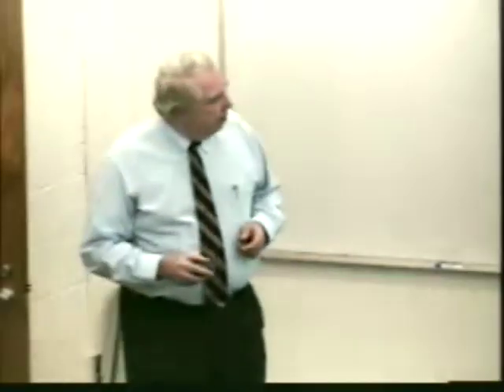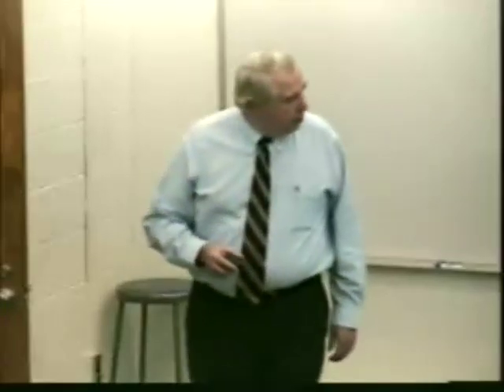There's one other interesting characteristic about this. General Electric has done a lot of design work on their liquid metal reactor. And in the case of their liquid metal reactor, where they have temperatures of 500 to 550 degrees Celsius, they have discovered, after lots of calculations and experiments, that the maximum size of their reactor can be about 1,000 megawatts electric. And the reason why is that as they go to higher power levels, there's simply not enough surface area in this vessel to transfer the heat in an emergency across to the air-cooled system. So the limit to this air-cooling system in a liquid metal fast reactor or some other type of reactor in the same temperature range is about 1,000 megawatts.